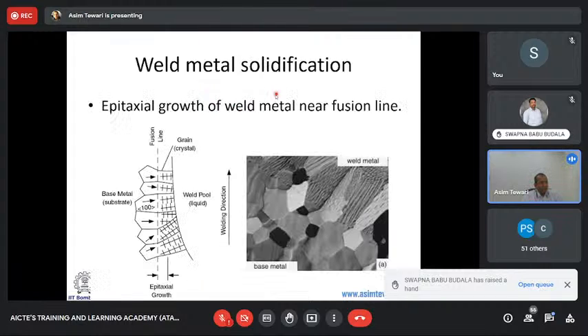Liquid could have another composition variation. And when you have a melt with another solid in its vicinity, which happens in welding and also in additive manufacturing, you start having a growth which is an epitaxial growth. That epitaxial growth leads to the liquid metal growing on the previous layered grains. So when a new layer is added, it grows on the previous layers, and that's how these grains grow on the previous layers.